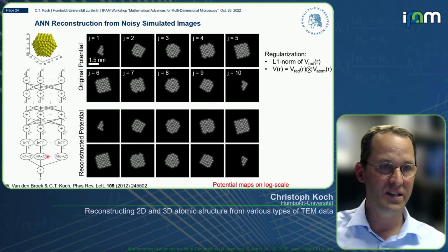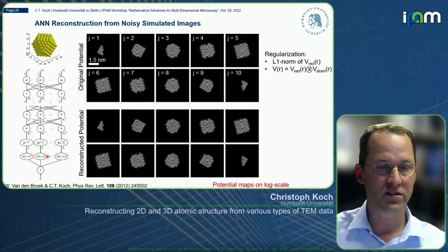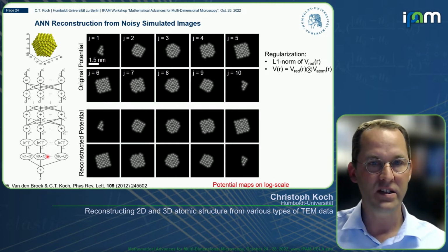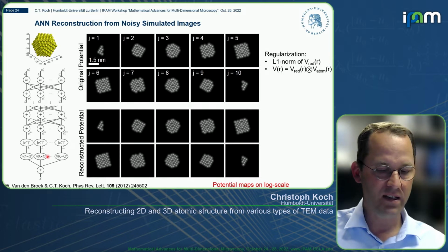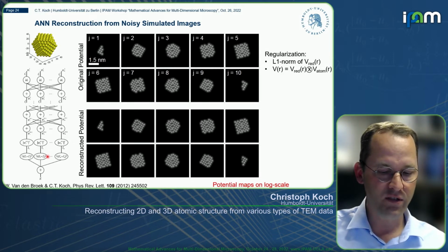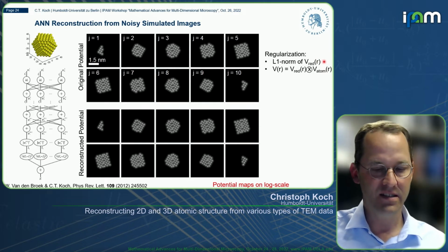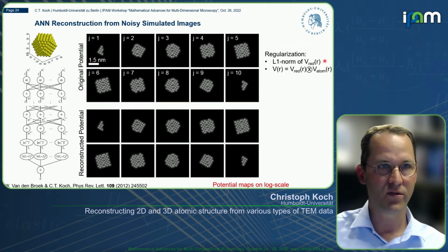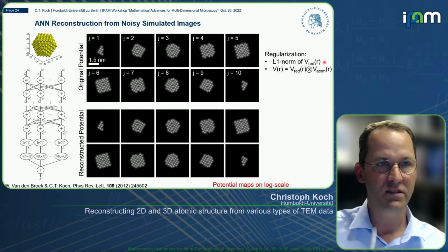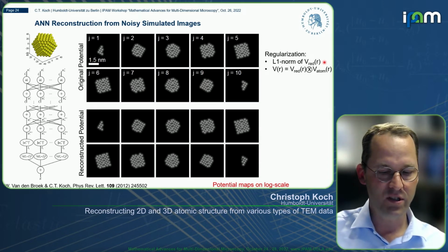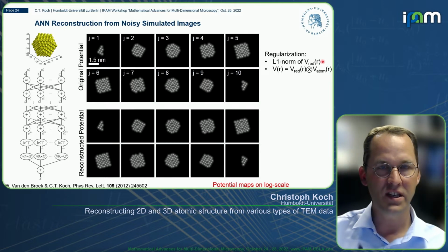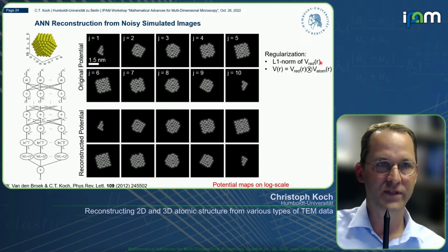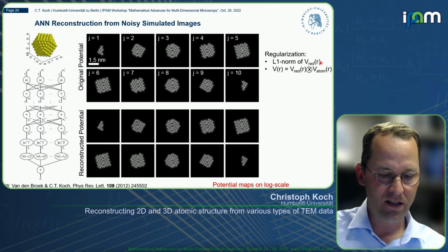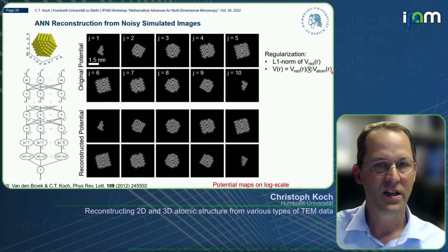And again, here we applied constraints to the reconstruction that we believe are physically reasonable. The constraint that we've applied is that the L1 norm of the reduced potential is minimized. So of course, as you know, this will lead to a peaky reconstruction. But what do I mean by reduced potential? The reduced potential is the potential that ideally should only have delta functions. And this reduced potential is then convolved with the atomic potential, because we know, of course, the scattering factors of our atoms are tabulated.